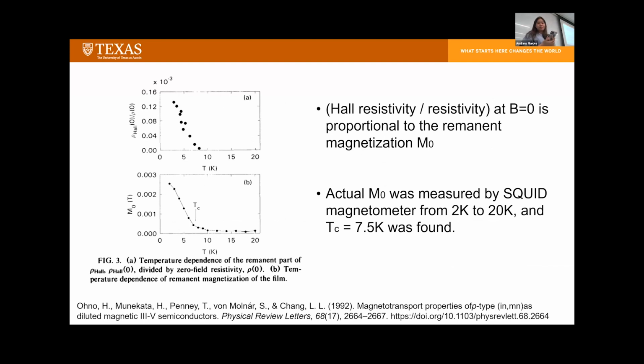Scientists measured the Hall resistivity versus the resistivity and made this plot. They also measured the remnant magnetization and made the second plot. They found that these two plots have a proportional relation, and it shows that the very first DMS obtained a Curie temperature around 7.5 K, also very low.